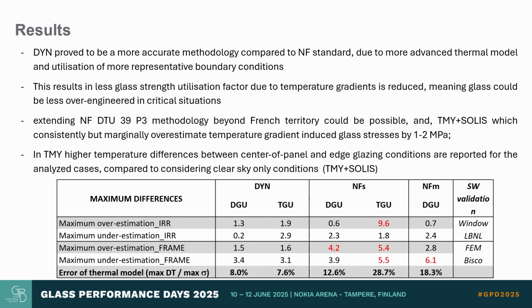We could extend the national standard methodology outside of French territory because we found a way to use the TMY representation to replicate those boundary conditions outside France, so we can simply extend that methodology. This, though, marginally overestimates the temperature-induced stresses by a few MPa. And then what we see is that in TMY with clear sky, we have a higher temperature stress.